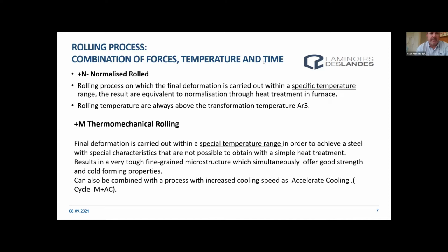Plus N is what we call normalized rolling. It is the process in which the final deformation is carried out within a specific temperature range. The result is equivalent to normalization through heat treatment in a furnace. In this case, the rolling temperature is always above the transformation temperature.